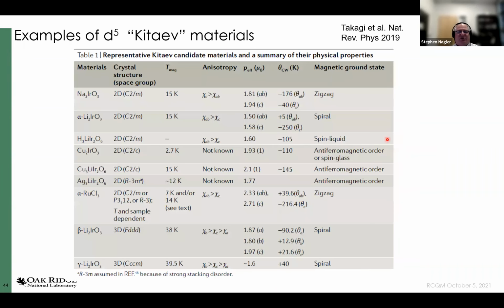So here are examples of these d5 electron-based Kitaev materials that have been investigated. Now, in this case, by Kitaev material, what I mean is that at least part of the spin Hamiltonian arguably contains these mutually incompatible, conflicting, competing Ising-like interactions. And if we want to say these systems are frustrated, we realize they're frustrated by competing interactions. So you can see there's a whole mess of iridates in here, some of which are honeycomb, some of which are hyperhoneycomb, and there's alpha ruthenium trichloride.